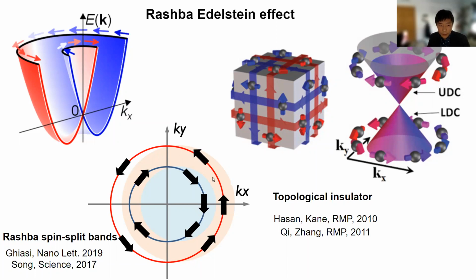So this type of spin texture, where the momentum and the spin are locked, implies that if you apply a charge current, which basically imparts a net momentum on the electrons, then that net momentum also implies a net spin polarization. Another way of visualizing this is that if you apply a current, you shift the Fermi surface, and that shift results in more occupation of the plus kx states versus the minus kx states. Hence you end up with a net spin polarization pointing along y.